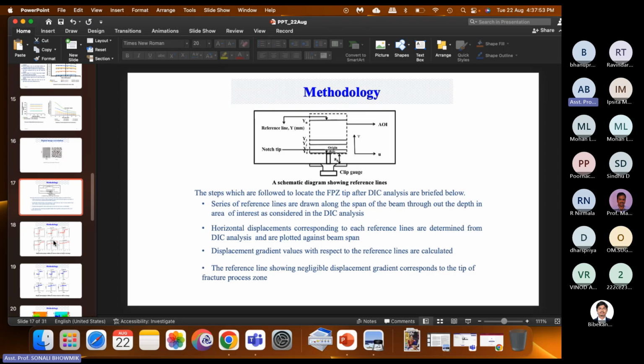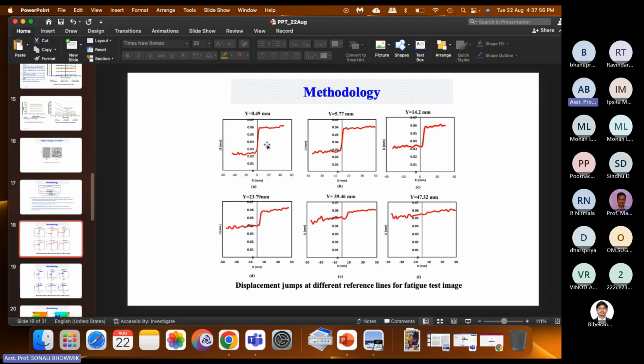So these things can be well understood with these plots. These are nothing but jumps. Near the crack tip you have an opening, and when you go upward, there will be a certain distance where there will be no crack opening. Since there is no jump, no crack opening, we can understand that this is the point after which there is no crack growth. And up to this point there is development of numerous micro cracks, and due to those micro cracks the crack got propagated.